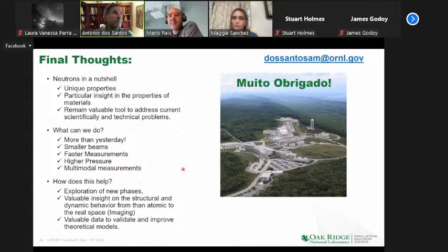I have a paper from a colleague that used the CO2 location in a MOF, because it was breathing. So as a function of pressure and temperature, some cavities would expand and allow the CO2 to go in, and then it would be locked in again. And then we could compare that with nitrogen, N2, for instance, and see how the same MOF would respond to different gases in a structurally different way. So you could see the CO2 contrast inside those cavities. It is challenging because they're very extended lattices, but it's powder. So if you can do it as powder, you do.